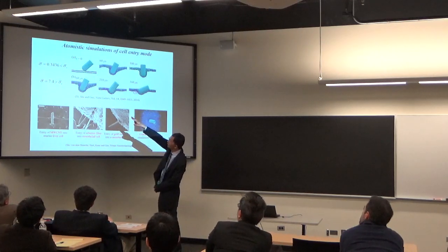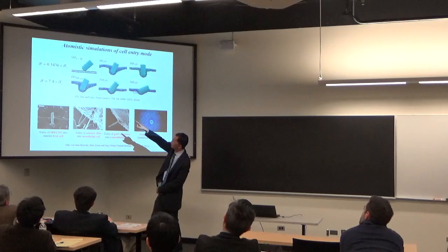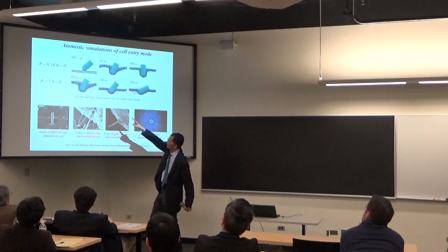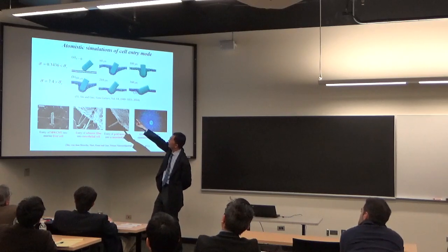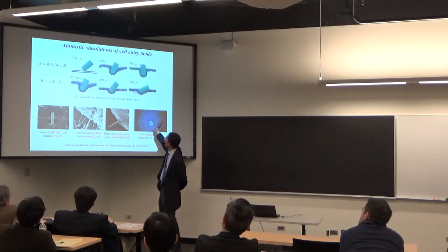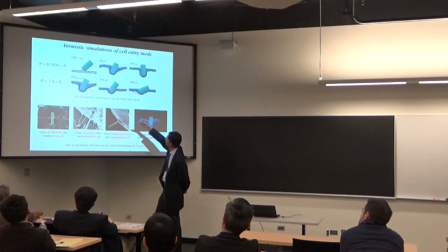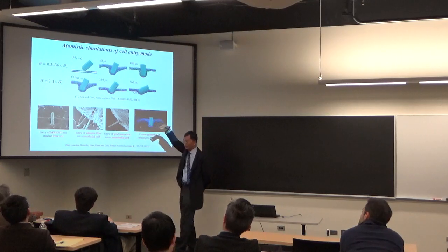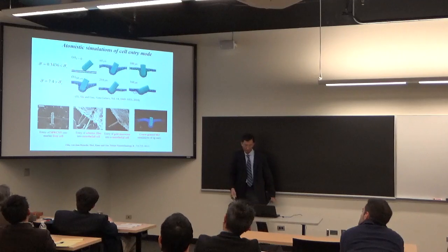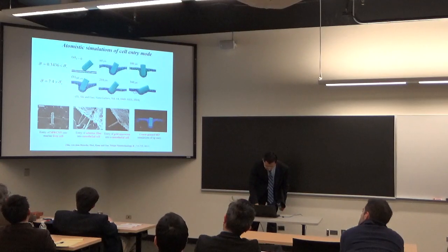But we can also tune the diameter, right? If the non-dimensional membrane tension we select is 0.3, the subcritical case, we see the orientation like this. If we select a big number, supercritical 7.4, then the nanomaterial will lie down, right? In full agreement with this.